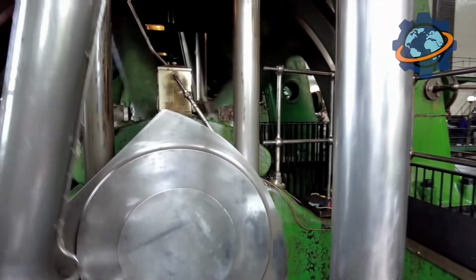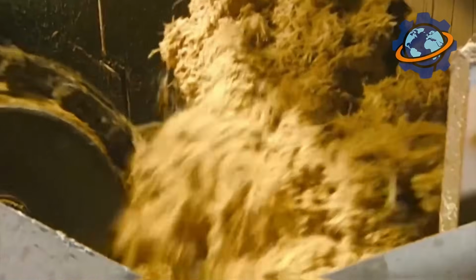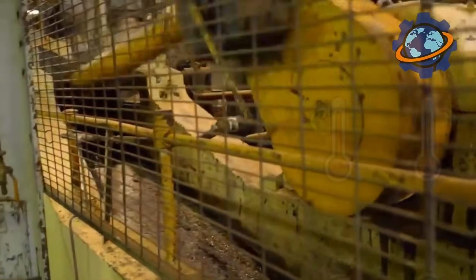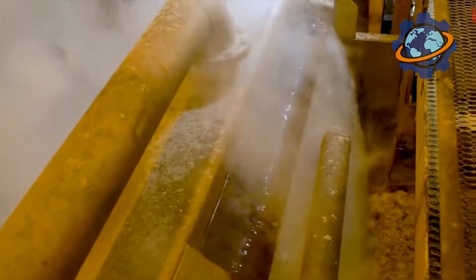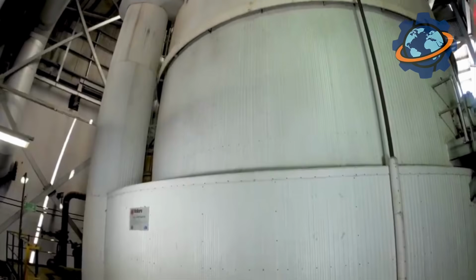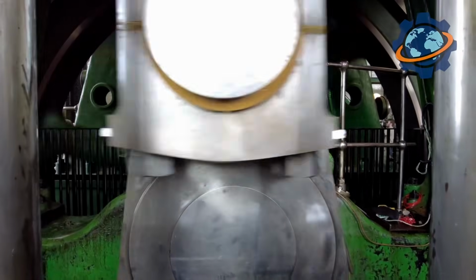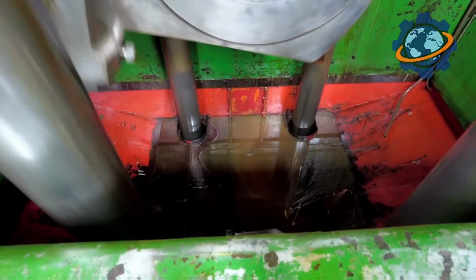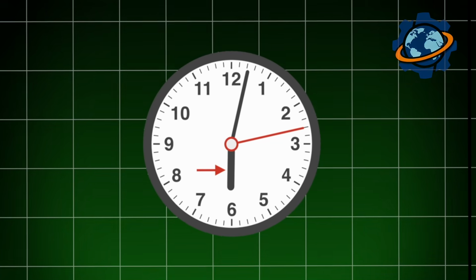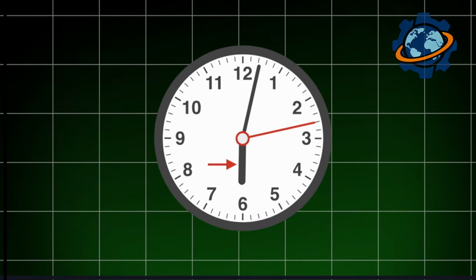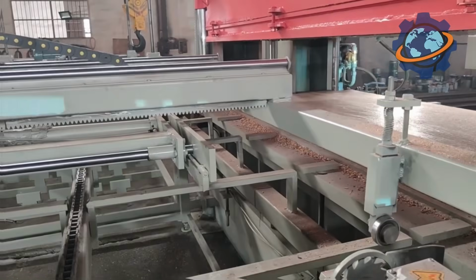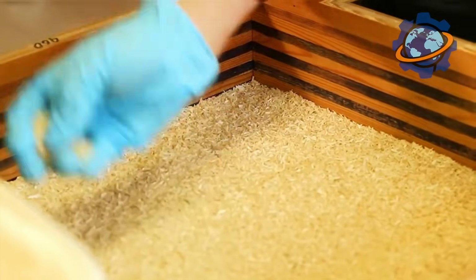Inside the press, the chip mass is simultaneously affected by 2 powerful factors. Huge pressure, reaching tens of kilograms per square centimeter, compresses the chips, leaving no voids between the particles. At the same time, the press platens, heated to a temperature of 400 degrees Fahrenheit, transfer their heat to the mat. This high temperature activates the resin, launching an irreversible polymerization process. The liquid glue instantly turns into an extremely hard and strong polymer, which permanently glues millions of wood particles together. The time spent in the press depends on the thickness of the board and usually lasts only a few minutes. During this short period, the loose mat turns into a hot, hard, and absolutely monolithic particle board.